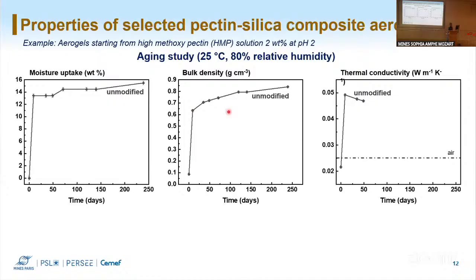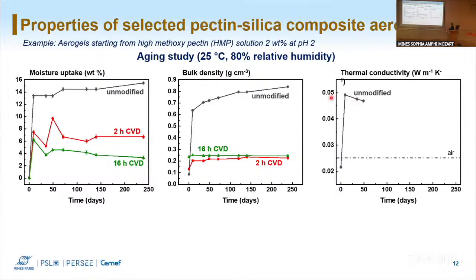And the same happens for thermal conductivity. So as we said, the unmodified pectin aerogels cannot be used as insulators as they are. When we do the deposition of the silica phase, we can see that the moisture uptake decreases a lot. So it's almost half. Then the bulk density increases slightly in the first day, but stays rather low compared to the neat pectin aerogels. And the thermal conductivity increases more substantially. This is the red line when we have 2 hours chemical vapor deposition, and for 16 hours deposition, the thermal conductivity stays nearly stable for the whole duration of the test, that was around 250 days.